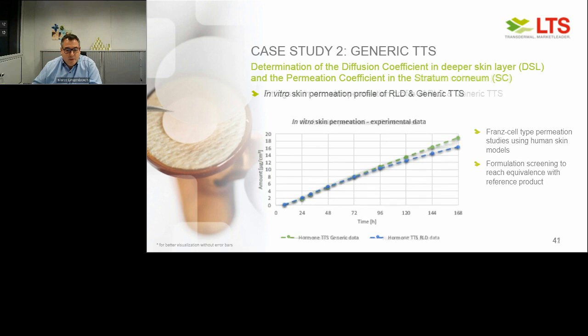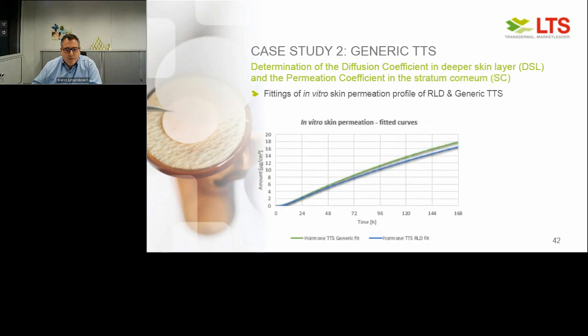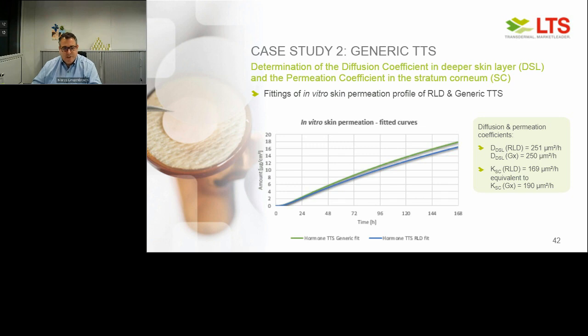Again, we do a fitting of these curves within our software, and by that we determine two different coefficients. One is the diffusion coefficient in the deeper skin layer, and the second is the permeation coefficient in the outer stratum corneum of the skin. The results show that in the deeper skin layers it's really, really identical, which is expected because the patch formulation makes no difference to the diffusion within the deeper skin layers. In the outer skin layer, it's already pretty equivalent, only with slight differences, which could, for example, be explained by different enhancer concentrations. So these are the in vitro data sets we're feeding into our software.